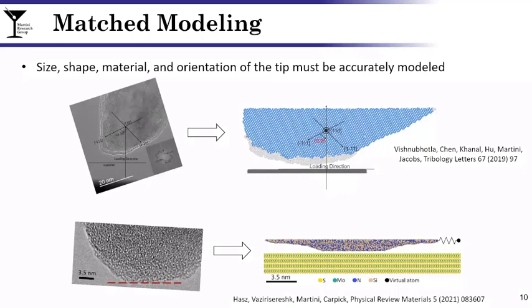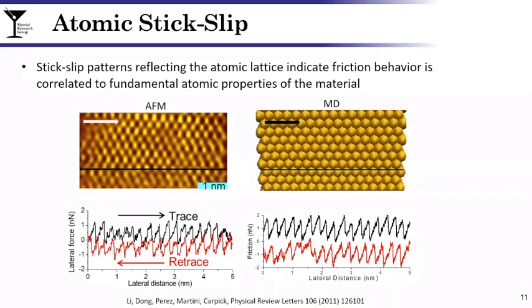So what's really important about this single asperity approach is illustrated on this slide. Shown on the left is our AFM results, and on the right are complementary molecular dynamics. The top two images are friction maps, and the bottom two are friction traces, meaning one line across the top one. The key feature in the lower images is the sawtooth pattern, and this corresponds to the tip sticking and slipping across the surface. The key feature here is that the periodicity of the stick-slip patterns corresponds to the underlying atomic lattice. This is a really powerful idea because we're trying to take this very complex frictional behavior and correlate it to a ground truth, to something fundamentally known. And there's nothing more fundamental than atomic lattice. So achieving this so-called atomic stick-slip is very important for using the single asperity approach to understand friction at a fundamental level.